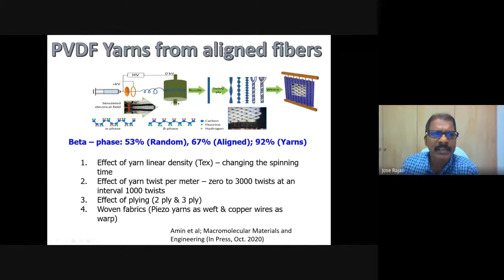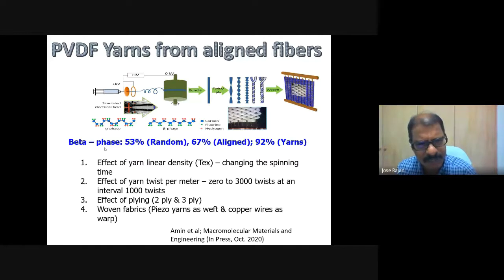And when we make yarns, we further apply mechanical stress to it. That one has a beta phase of about 92%, meaning almost the complete fraction of this PVDF yarn is beta phase. I think that is one of the best results achieved so far. And in this one, we have systematically investigated the effect of different things. For example, the effect of yarn linear density or TEX. People from a textile engineering background know this parameter TEX.